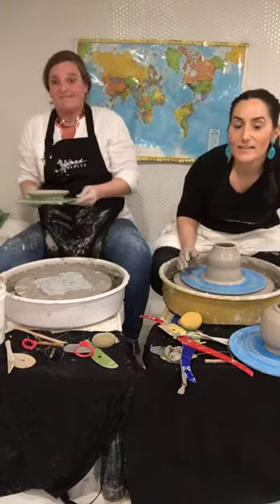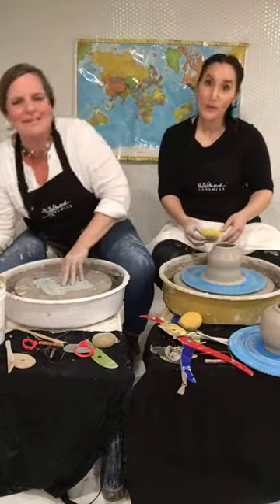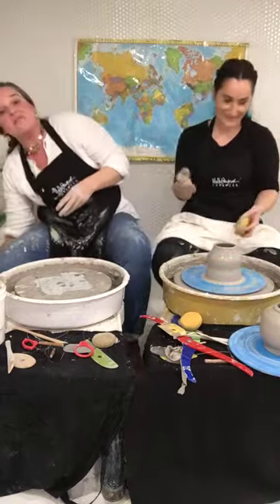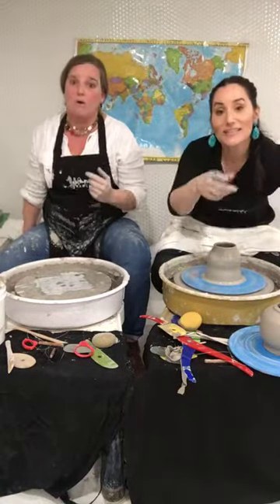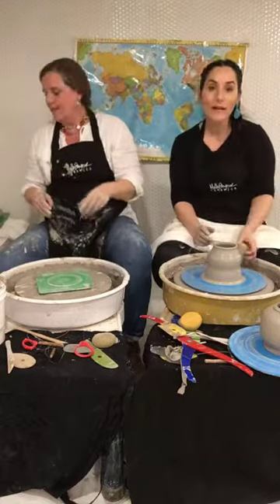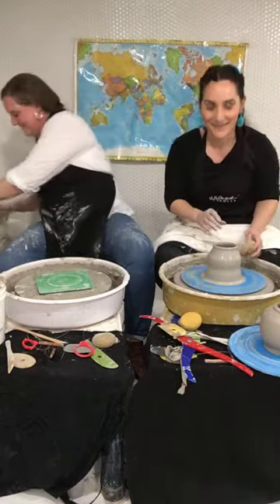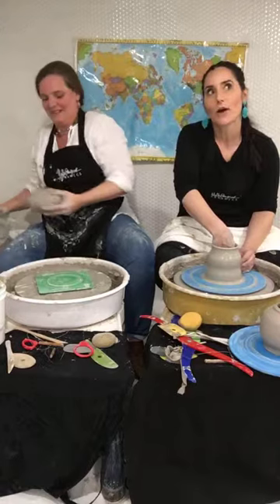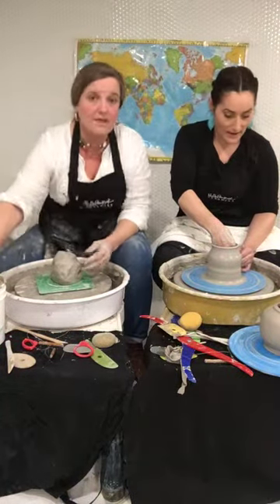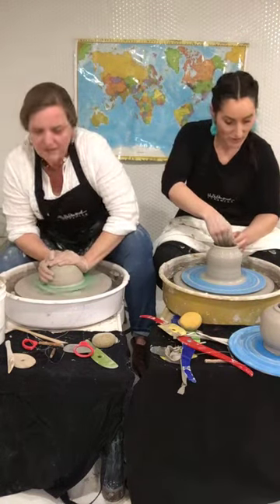You have to be philosophical. That's another way we're yin and yang — we'll have an explosion and Amy's like, 'The spirit of the clay,' and I'm like, 'Your pot was too wet, it was too thick, we fired it too fast and didn't preheat it.' My favorite thing is when you say to the kids, 'Is this hollow?' And they're like, 'Oh yeah, it's hollow.' I'm like, I don't see a pinhole — it ain't hollow. Guess what, guys — we unloaded that kiln and it exploded. I think that's the learning though: reflect on why things would explode, not about the feelings but why did it break, so it doesn't happen again. Always a learning tool.